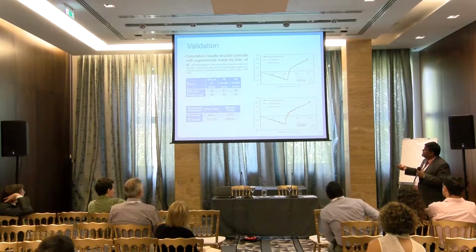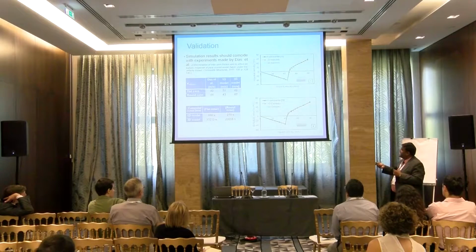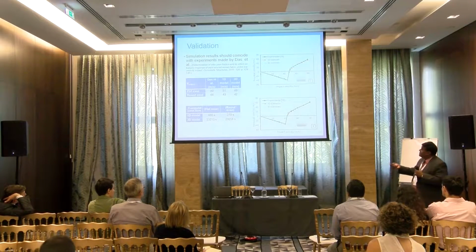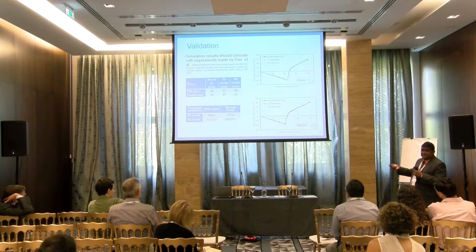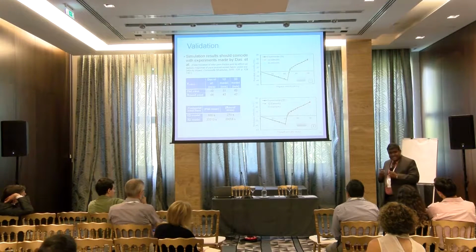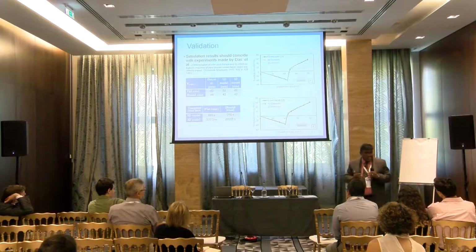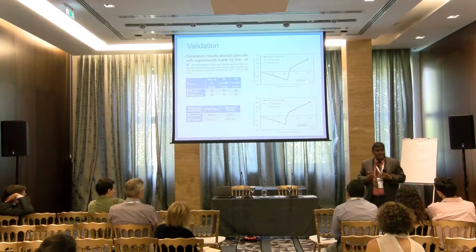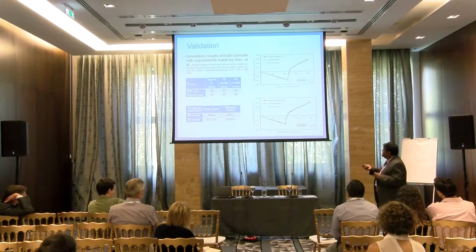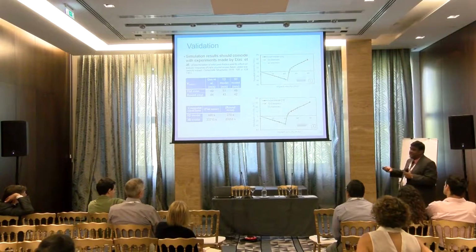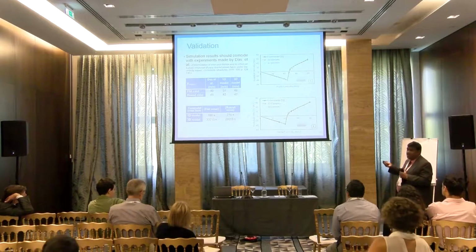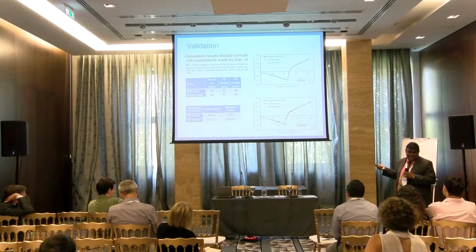And we can see the limiting velocity for the 1D model and 3D model are very close for both the flat case and round case. And it compares very well with this experimental data as well. So we are very satisfied that this 1D simplified model does reproduce the effective 3D model very accurately in terms of calculating the limiting velocity, or what we call critical velocity. Not only that, it does match very well with experimental data. So we are very confident we can move forward with this model for our parametric study.